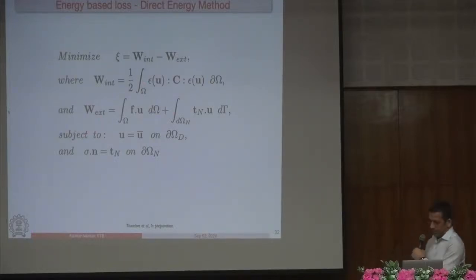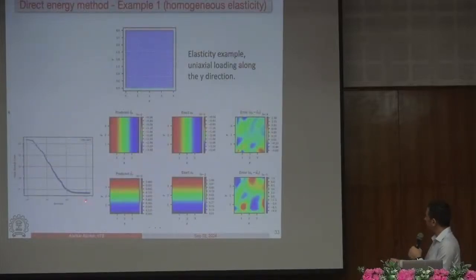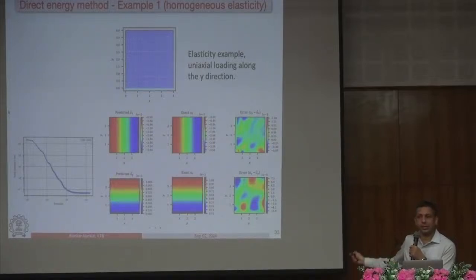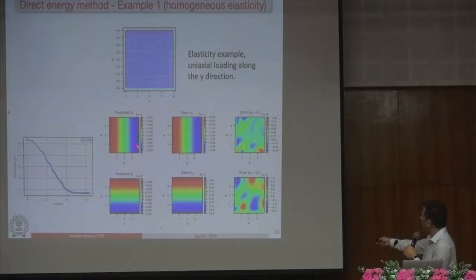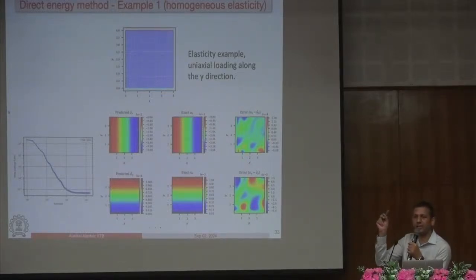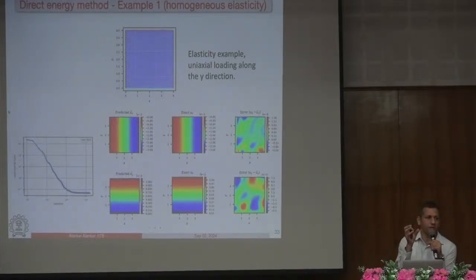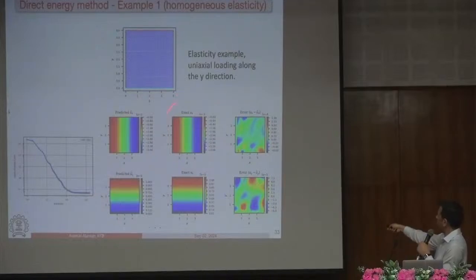So this is my new loss function. And by doing that, the numbers are very small, but I can read you that these are just 1000 iterations of the same physics informed neural network. By doing only 1000 iterations, we were able to bring the loss to 0.04 times 10 raised to minus 2, 0.0004. Earlier, the loss was 0.36 in 10,000 iterations. That means if you have a sophisticated loss function, which is also capturing thermodynamics, you can accelerate your machine learning simulation as well. So this is a very simple domain, and not of much practical purpose.